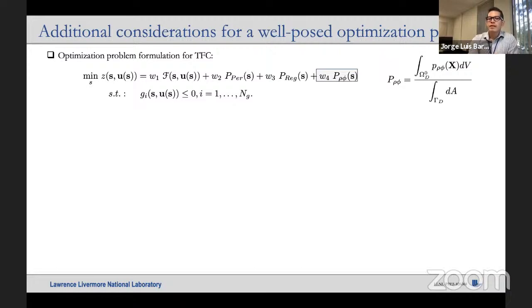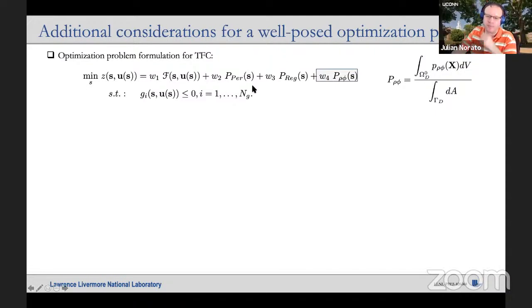But you have a good point, in the sense that the keyword here is contributions. One thing is what numbers you assign to this weight, and a different one is what's the actual contribution to your objective, because this affects your sensitivities and how your problem performs. In this case, I mentioned that they were normalized, and that's fine. But you have to be careful for other non-standard problem formulations. If you don't see this as compliance, but something non-structural, like your chemical potential or something that grows exponentially, then you have to use something like a logarithm to avoid orders of magnitude of difference between this and this other one. Then you're no longer minimizing what you actually care about. So yeah, you're right there.